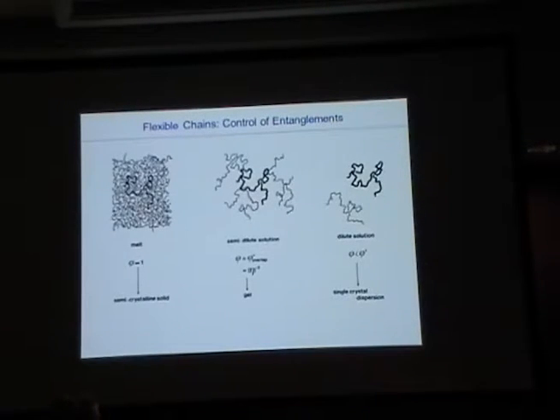Okay, so here is how we can control the microstructure. We can have the melt of a polymer. So you see it's quite a mess, many, many entanglements. And if you want to get them crystallized from the melt, either you really have to cool it very, very slowly, or what we usually do, you have to go to semi-diluted solutions, so you have still a few entanglements. Usually we don't like to go to very diluted solutions, then we really separate all the chains.